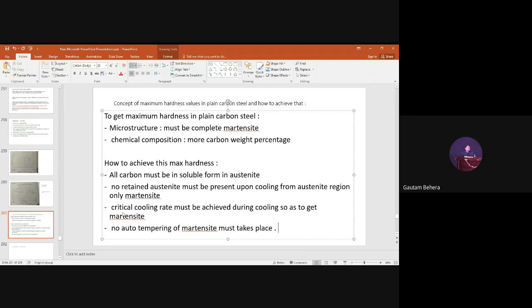And if you temper for a long time, a lot of carbon will come out. Finally, you will end up with a ferrite matrix with spherical cementite precipitates. Ferrite matrix means it is very soft and tougher. Some intermediate carbides form, like epsilon carbide, Fe2.4C, during this process. Some recovery also takes place, and carbon moves to dislocation sites or any defects. So these are the things that happen during the tempering process.